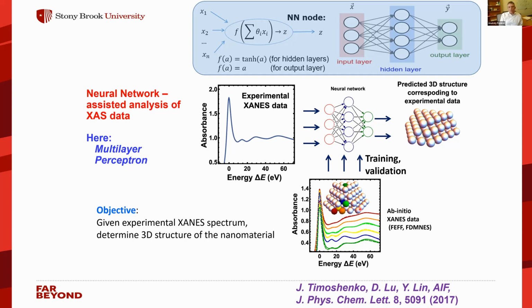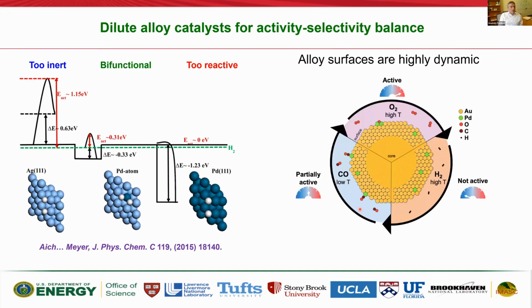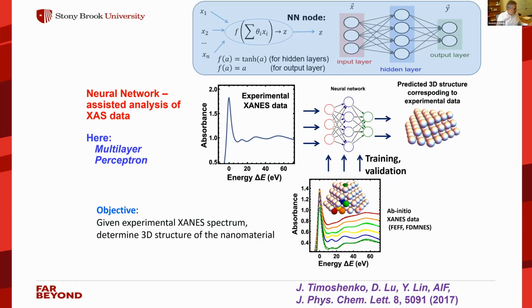So by that, we were able to train our neural network. And then when we fed our experimental data, it was able to predict the same coordination numbers as we could obtain independently. And we published it over many papers in well-defined nanoparticles that back then we did not know that we need to reanalyze them, but now we analyze them by EXAFS and obtain the same results. So that's how we knew that the method works. So this is the first part of my story.